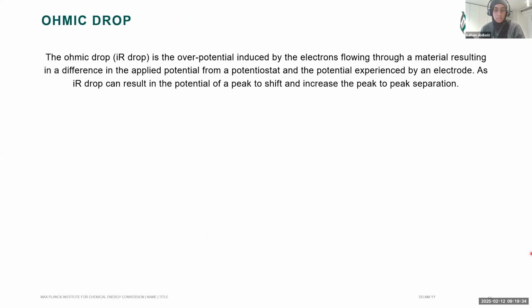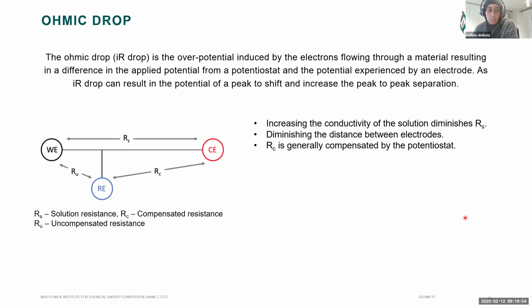There is one parameter that is quite important in electrochemistry, which is the ohmic drop. This refers to the voltage that's lost due to the resistance in your electrolyte or somewhere in your system. And so you have several things that can cause an ohmic drop, which includes solution resistance. If your solution is not sufficiently conductive, you get resistance from your solution, and that adds to your ohmic drop. You can have uncompensated and compensated resistance, which comes from distances between the electrodes. All of these add to your ohmic drop, which means that the potential that you're applying from the potentiostat is not necessarily the same as the potential that's experienced at the electrode.